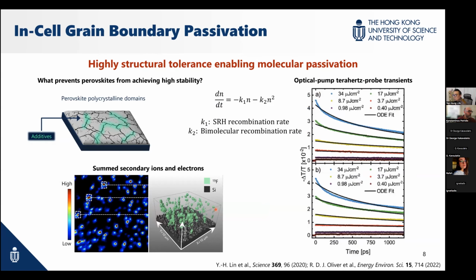But for most of the work you see from the community, we do, as part of the community, some optical spectroscopic characterization. For example, we also did the same things like optical pump terahertz probe tracings here. Comparing these two, one is the modified film, the other one is the control film. There's not much difference. So what it indicates, I'm just going to jump to the conclusion: basically, the modification doesn't modify the electronic structure. The electronic structure remains the same. So this property is the same.